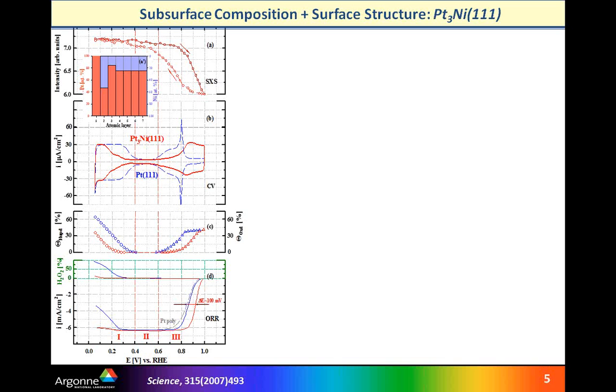First of all, what we can see on the top is a unique, I would say, anomalous scattering result, which for the very first time established that in an electrochemical environment, platinum-nickel surfaces, in this particular case platinum-3 nickel 111 surfaces, are segregated. I am considering this one of our biggest achievements, because now we know exactly what is on the surface. It's almost pure platinum. This is what we call the platinum skin. And this platinum skin, as we can see below in the electrochemical result, has unique electrochemical behavior.